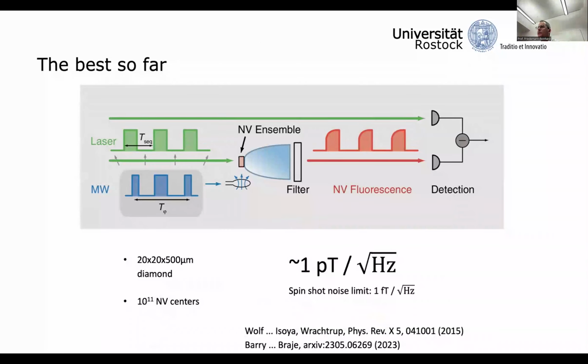Now, that is a bit surprising. And even to only get to this level, a lot of effort was necessary. Typically, these best published experiments use a carefully prepared, very clean, but densely NV-doped diamond, carefully engineered collection optics, parabolic collectors, and complicated sequences with lock-in detection and other tricks to compensate for technical fluctuations of parameters like microwave power and so on.